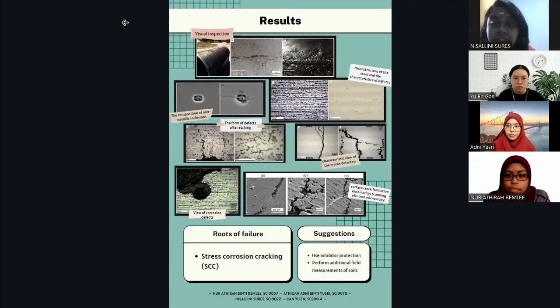Aside from that, it depicts a typical view of the fractures identified in the gas pipes section with a depth of 4 to 5 mm, which is 40 to 50% of the pipe's wall thickness. Following that, a pipe surface with a metal corrosion flaw is depicted in the context of corrosion defects. However, there are no cracks in the corrosion pitting's bottom. Finally, SEM examination revealed that the studied steel's microstructure conforms to a ferrite pearlite structure with considerable banding. Corrosion develops along the borders of ferrite grains, and the arrows indicate the source of corrosion damage along the boundaries of ferrite grains. That's all from me.